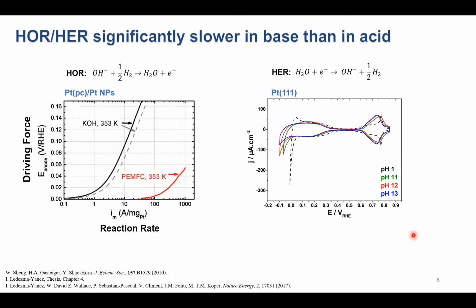Something that I've been interested in studying for the last few years is looking at the pH dependence of the hydrogen oxidation and hydrogen evolution reactions, where it's found that on many active catalysts, the rate of both of these reactions is significantly slower in an alkaline electrolyte than in an acid electrolyte. This is shown on polycrystalline platinum in the figure on the left here, where we have the overpotential, or the driving force to drive hydrogen oxidation forward, versus the rates of the reaction. And we can see that at any given potential, any given driving force, the rate is 2 to 3 orders of magnitude higher in the acid electrolyte shown in red than in the alkaline electrolyte shown in black. Right, so this is a huge effect.